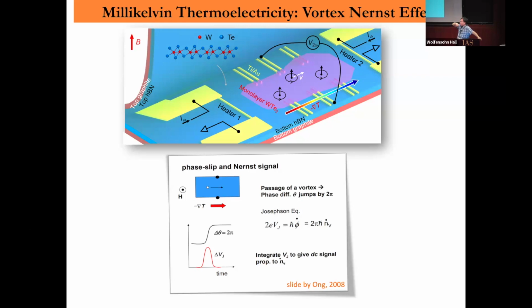Now, if you move your vortex, what does that mean? The phase near the electrodes will change as a function of time because of the moving vortex. Which means, if I consider the phase difference between these two contacts, the phase here, very far away, is 0, and the other direction you have 2 pi. So you will see a change of the phase between the two electrodes by 2 pi, like this.